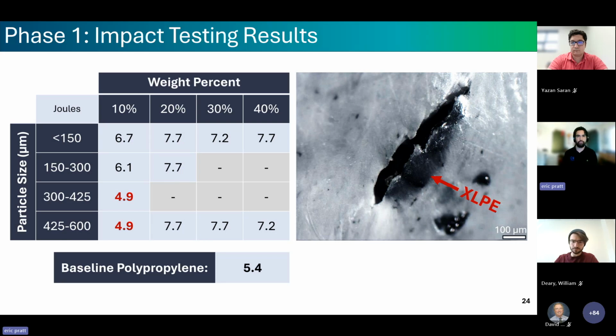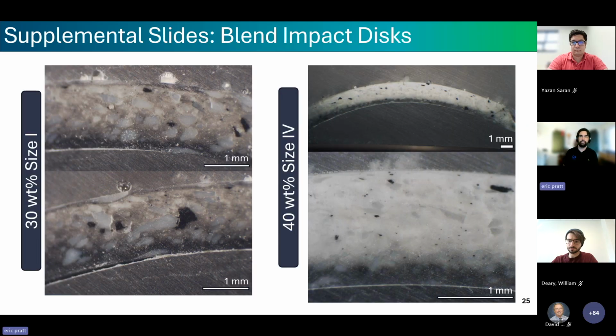So what we get here is essentially a threshold effect. Below 10%, there's a significant effect of the particle size, and above it, there is no significant difference. And we can see that mechanism here in our tested samples. On the right, at 40 weight% with our largest particle size, the fracture surface shows some discoloration in a band around the edge. This is clear evidence of the interfacial delamination concentrated in one region.